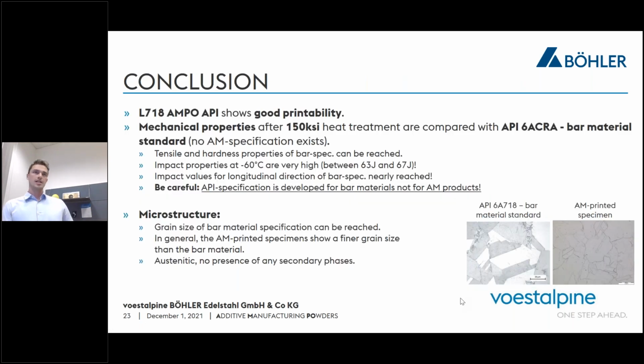So in conclusion, you can say that this L718 AMPO API showed good printability. The mechanical properties, if you compare it to the API 6 ACRA bar material, you can reach the tensile and hardness properties of the bar specification. The impact properties at -60 degrees C are very high, so as I pointed out, between 63 and 67 joule. The impact values for longitudinal direction of bar specification are nearly reached. However, this is not really important when it comes to industrial standardized tests.